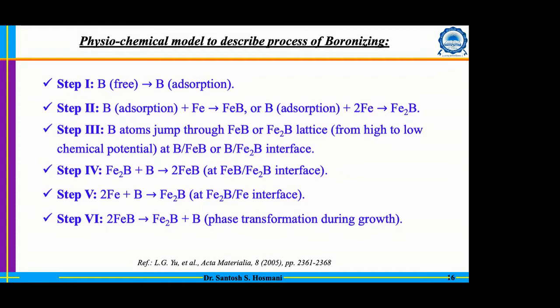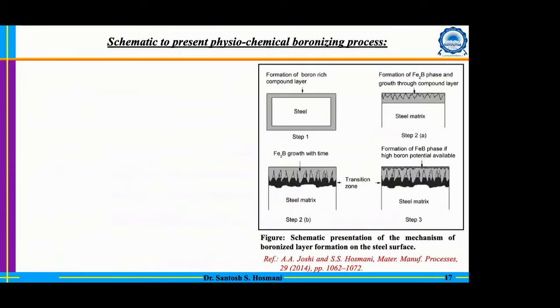Obviously, the system wants to grow both layers together. That means the FeB layer will grow together with the growth of the Fe2B layer. That means at the surface, to achieve the equilibrium between these two compounds, there is a possibility that there will be some kind of dissolution of FeB into Fe2B, or vice versa, Fe2B into FeB. So those reactions can occur at the surface during the growth. And this is the simple mechanism that people have proposed, and this is from our work.